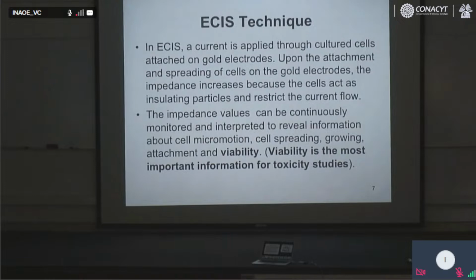Then the cells are spreading, and then they form a very nice monolayer. Meanwhile, the impedance increases because the cells act as insulating particles and restrict the current flow. Now, the impedance values can be continuously monitored and interpreted to reveal information about cell micromotions, cell spreading, growing, attachment, and what is important for us, viability. This is the most important information for toxicity studies.